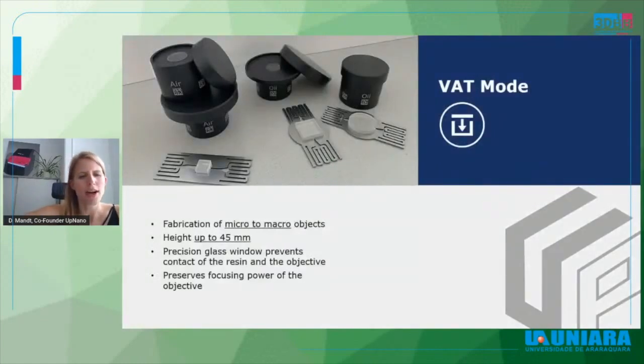So this basically covers the whole range, printing from micro to macro objects, with a height of up to 45 millimeters. We have different setups depending on the substrates, smaller ones and also bigger ones, and then the corresponding vats to put the material in. The vat has a small thin glass window in the middle. This prevents the contact of the objective and the material you are putting into the vat, and also preserves the focusing power of the objective.